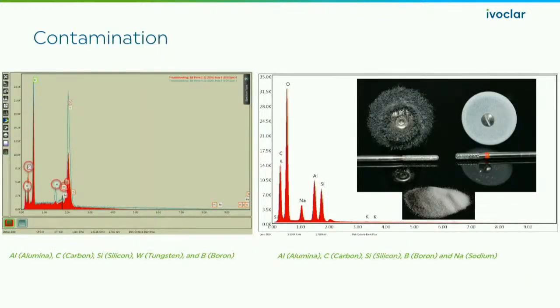This is one I did. One of the first complaints came in, and I did some testing with the materials. The analysis on the left was the spots I found on the crowns, and the analysis on the right are of those materials. We don't put tungsten or boron or carbon or silicon all in at this level. Silicon, yes, there's a little bit, but not to this level. Alumina, there's alumina in there, but not to the level we're seeing.